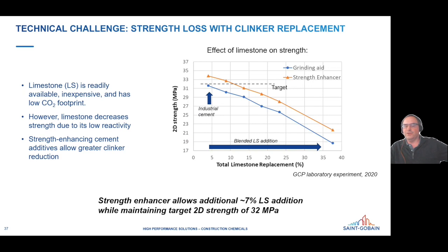So in this case, we've taken an industrial cement, and this is the blue curve here, and we've just diluted it with ground limestone in the lab. So we've gone up to 10, 15, 20, 35% limestone blended into the cement. And then we're measuring here the two-day strength, and it obviously just declines because limestone is more or less inert.